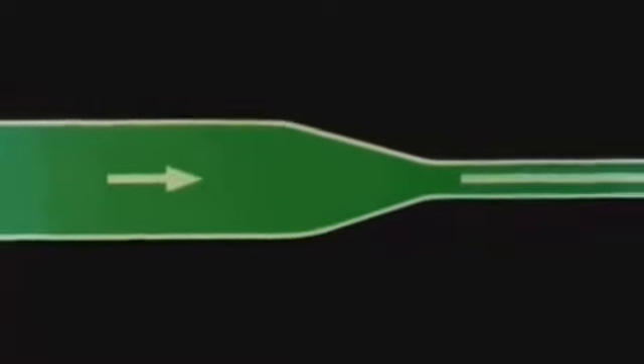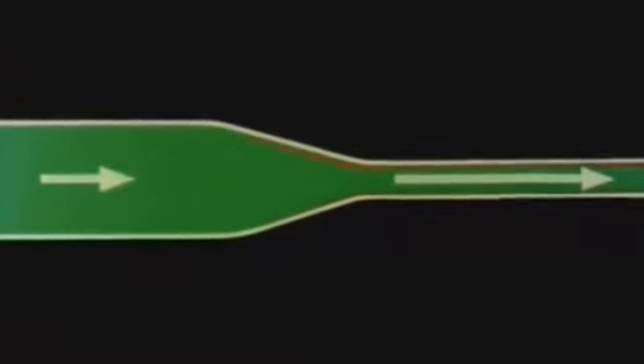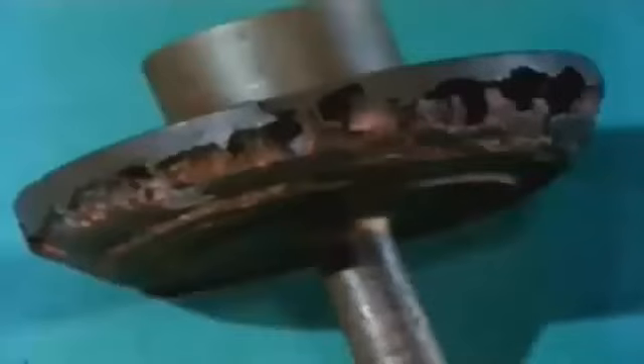Metals which corrode slowly will often be protected by the corrosion products left on their surface. So that if a liquid is moving slowly, there will be an acceptably low rate of corrosion. But rapid flow or turbulence may remove the protective layer and permit severe corrosion. This is termed erosion corrosion. It can occur in any situation which increases liquid flow sufficiently. In a seawater pipe, as a valve closed, the rush of water increased and removed the protective oxide layers. Erosion corrosion occurred. The remedy for the designer is to use either a larger valve or a more corrosion-resistant material.